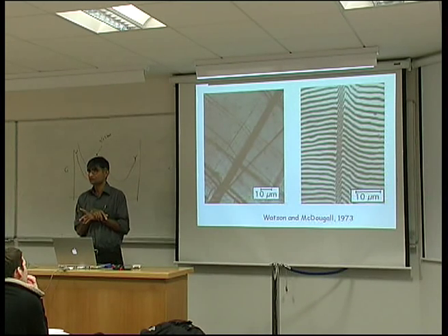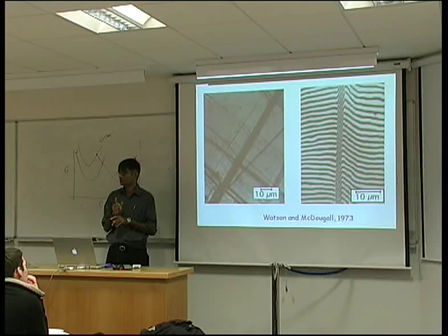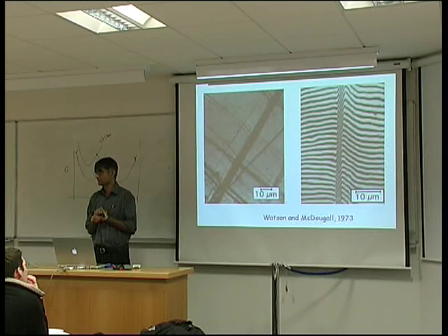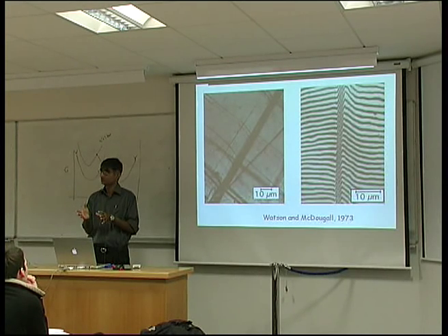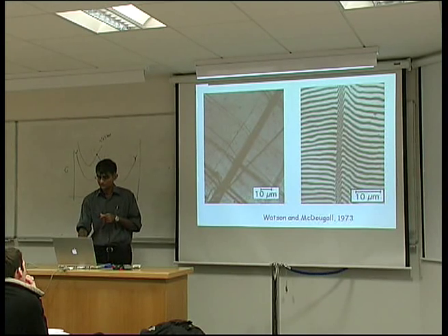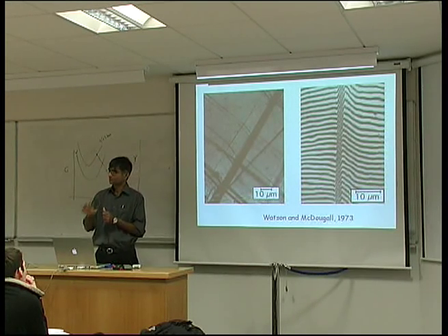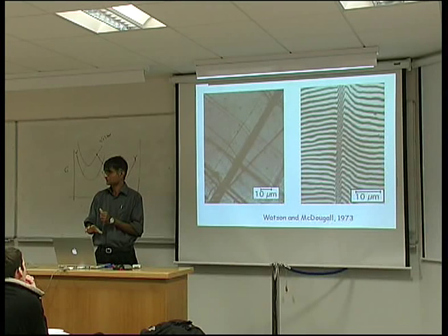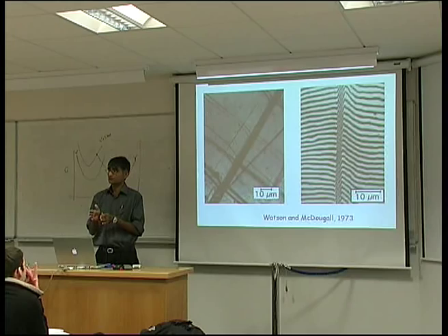It is impossible for it to be diffusionless. The carbon, which is the interstitial atom, partitions during the growth of these plates. So it is truly a paraequilibrium transformation, where the substitutional lattice is displaced. So you change the crystal structure by a deformation, but the deformation occurs at a rate which allows the carbon atoms to partition. So it is not even possible for this to be a diffusionless transformation.